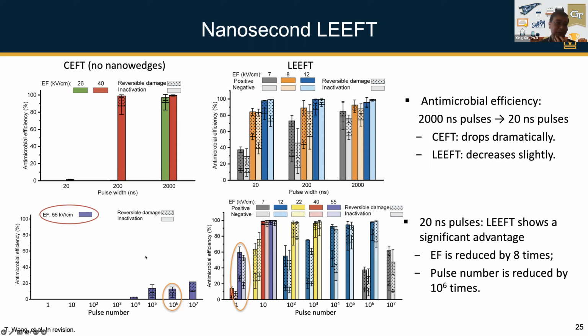I think that's even more exciting, that you can achieve a similar level of inactivation. In this case, with the conventional method, you need to apply basically 10 to the 6 pulses with the 20 nanosecond pulse. But with our system, you only need 1 pulse of the 20 nanosecond electric field, and you can achieve even better inactivation. Okay, so we haven't published this paper yet. It's still in revision. Hopefully we'll get it published, and you'll be able to see our detailed results pretty soon.